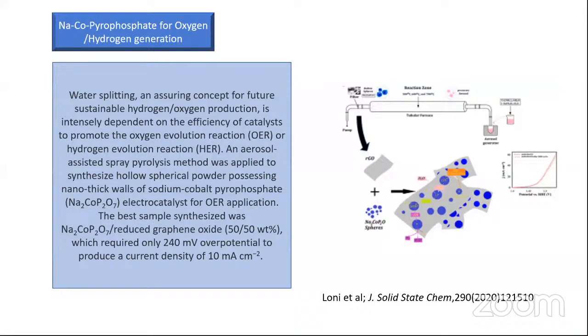An aerosol assisted spray pyrolysis method was applied to synthesize hollow spherical powder possessing nanothick walls as an electrocatalyst for OER application. The best sample synthesized was sodium cobalt pyrophosphate with reduced graphene oxide at 50% weight, which required only 240 millivolt overpotential to produce a current density of 10 milliampere per centimeter square. So this research was recently reported in 2020.